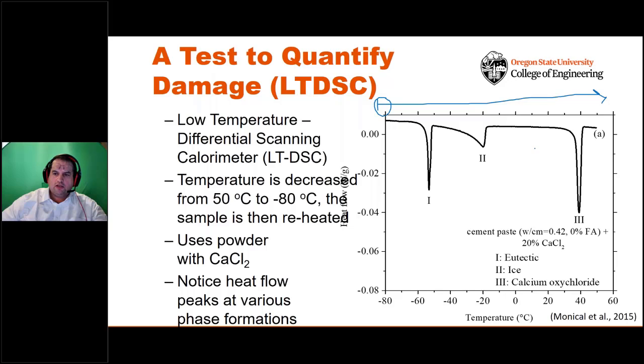What you'll notice is if we had no reactions taking place, we'd have essentially a flat line. However, you can see 3 peaks or 3 dips in this system, 1, 2, and 3. The first one is that eutectic solution going from a solid to a liquid. It happens at about minus 52 degrees Celsius. It happens at exactly the right place. And the area under this curve is simply the amount of that material that's taking place.